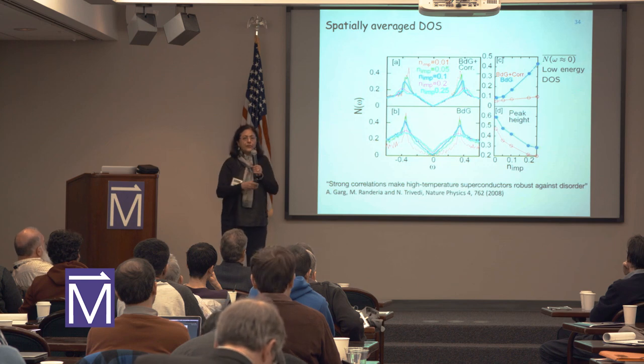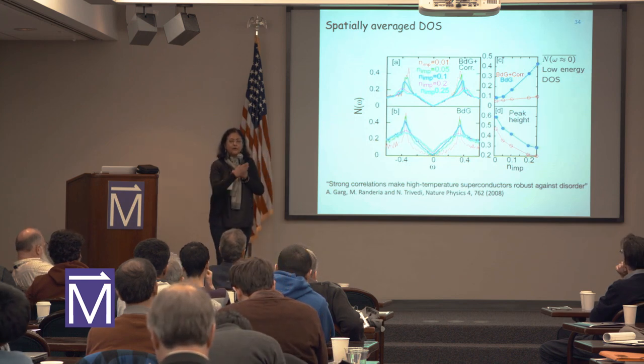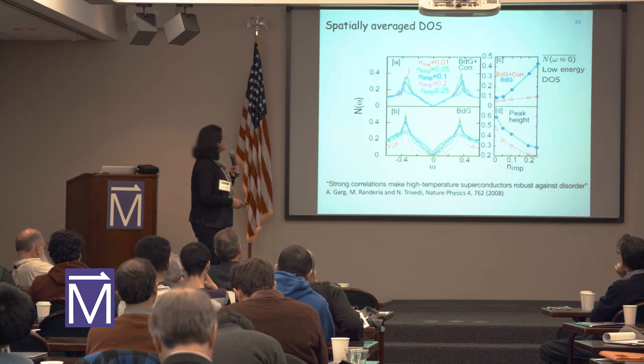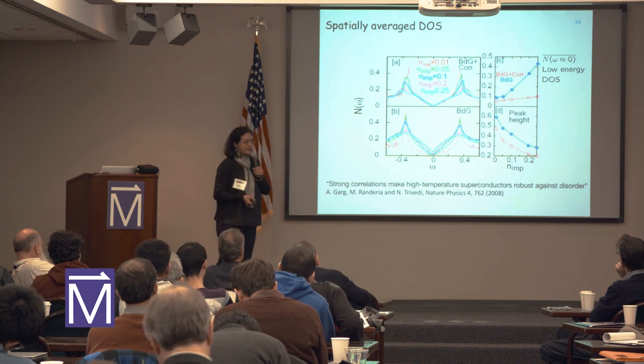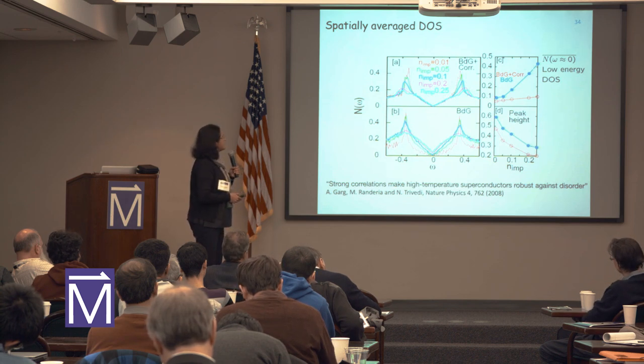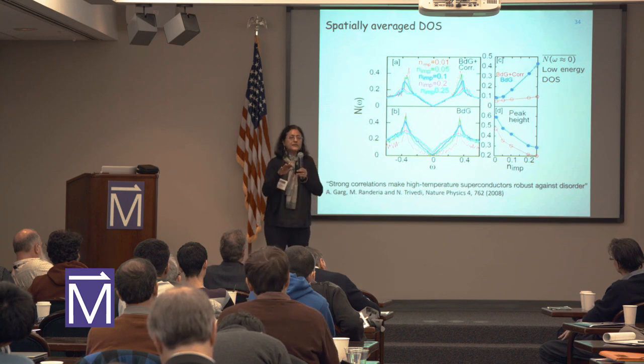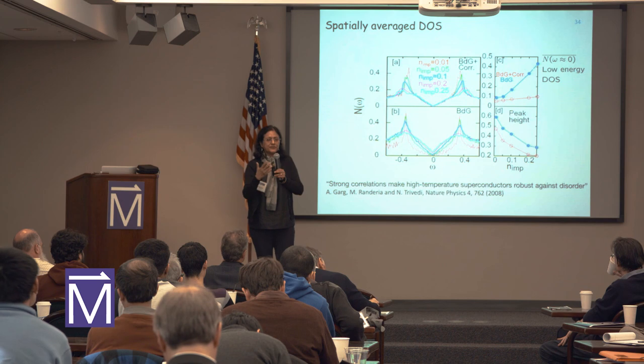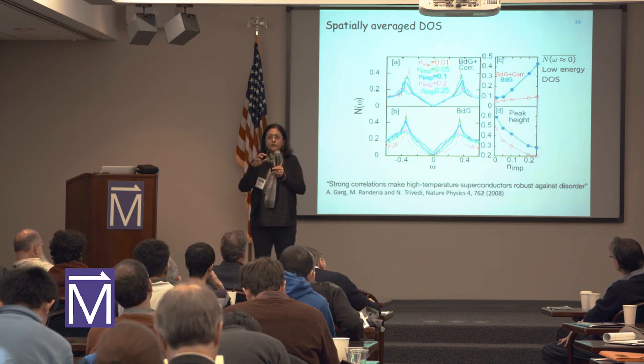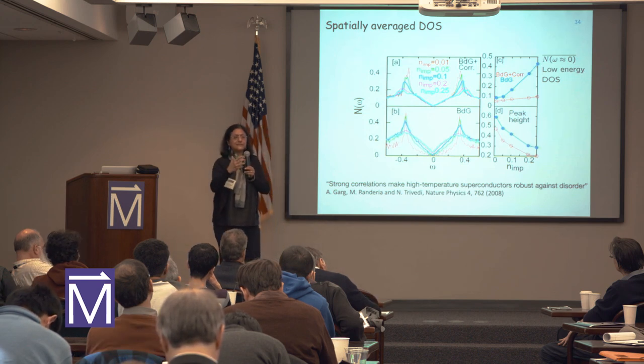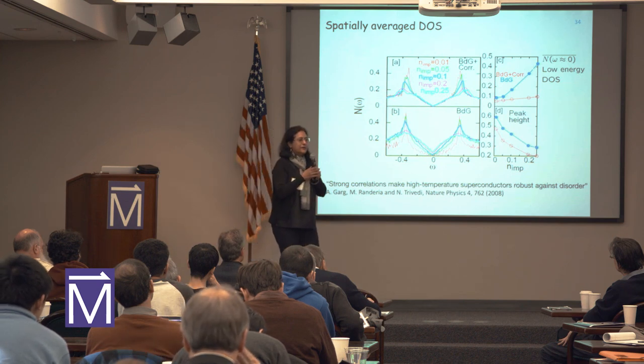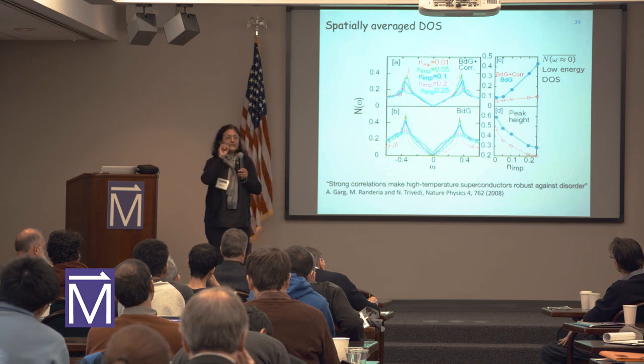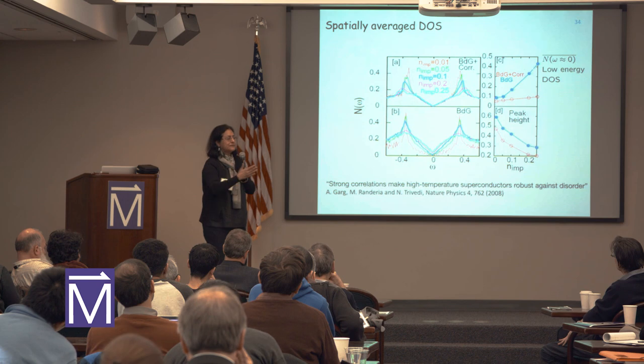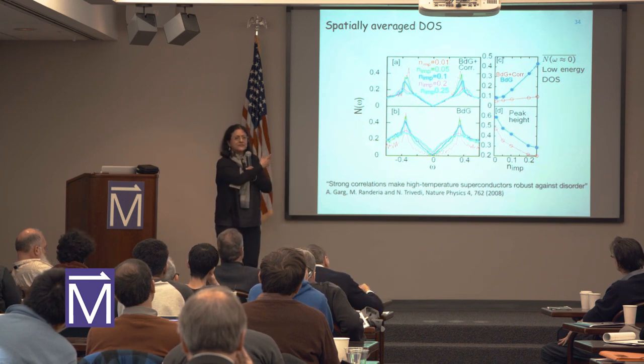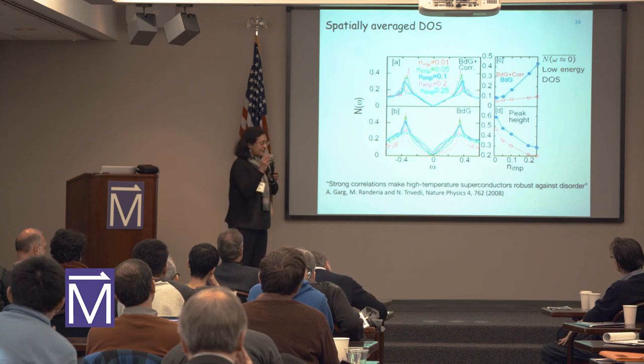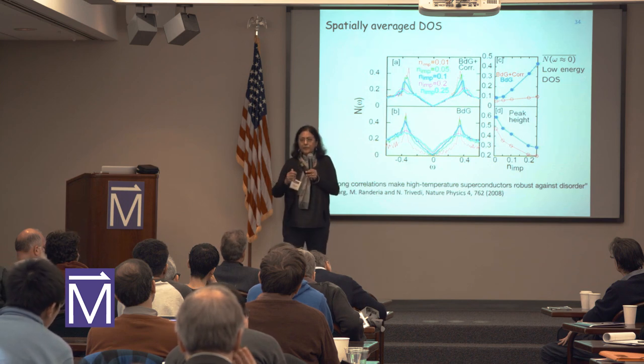But now that we have the numerics, we were able to go into this and dissect the origin of where this phenomenon is coming from. And a lot of this discussion happened with Lev Gorkov. I'm only going to give you a small gist here. And that is just to say that the crucial thing in destroying this low energy protection is that in a D-wave superconductor, you have lobes of your order parameter that have positive and negative phases. That's the structure of the D-wave function. Now, if the disorder could only scatter within one of the lobes, you would protect the gap structure. But at these degrees of disorder, 25%, you're not really going to prevent internodal scattering.